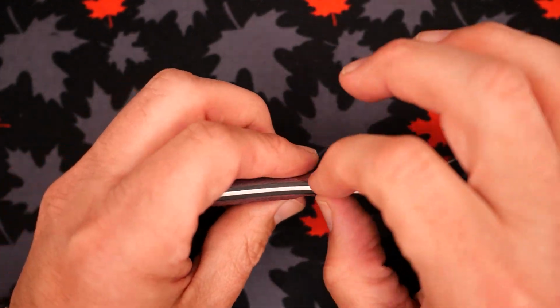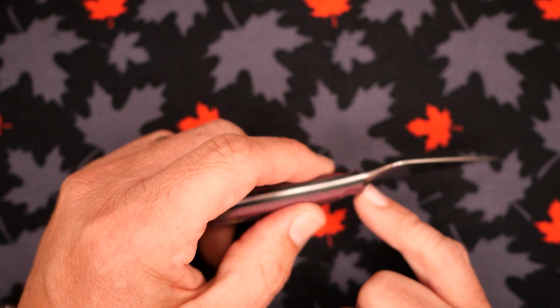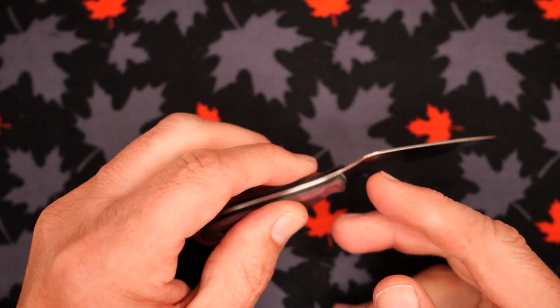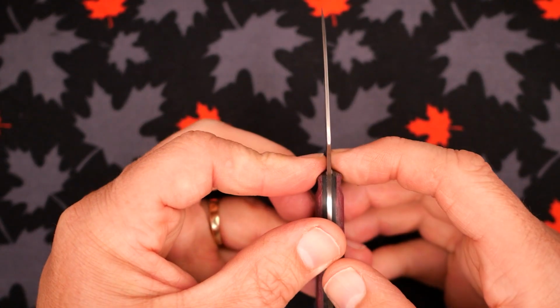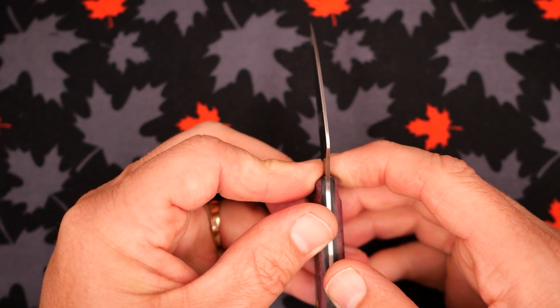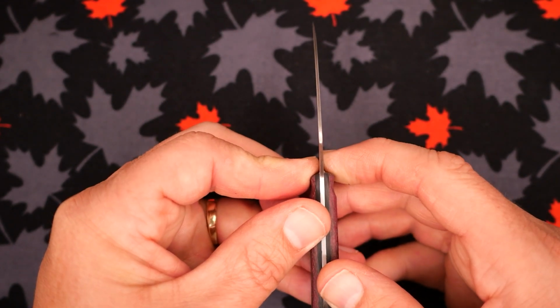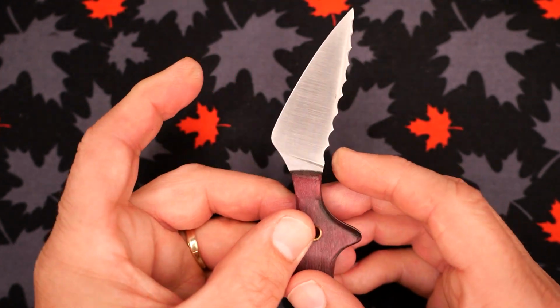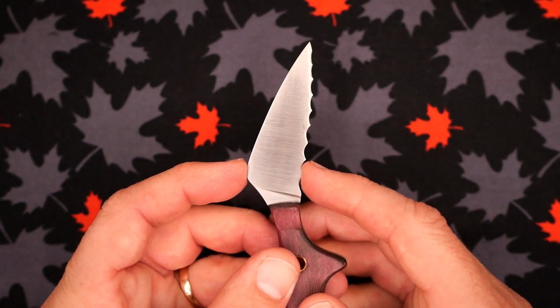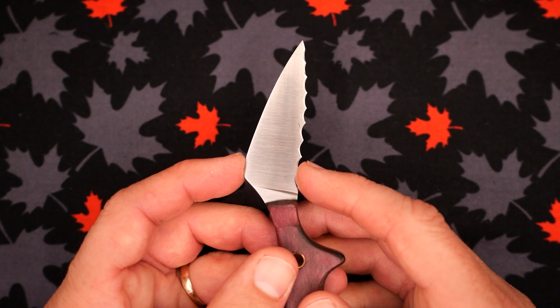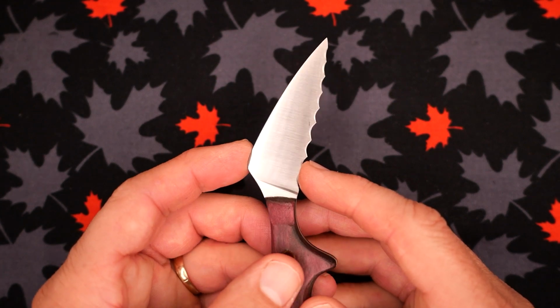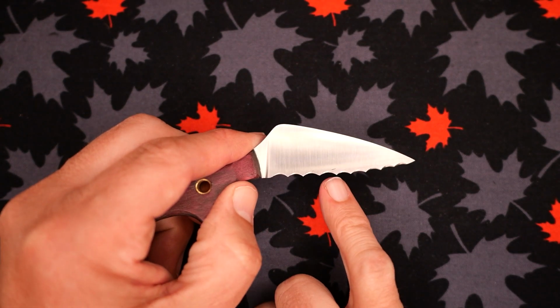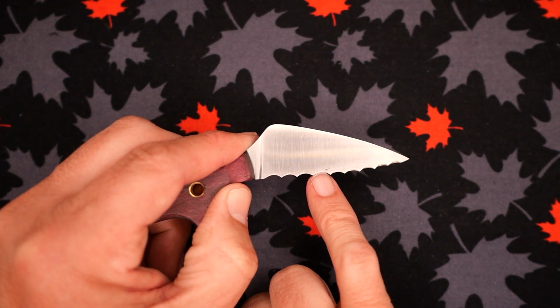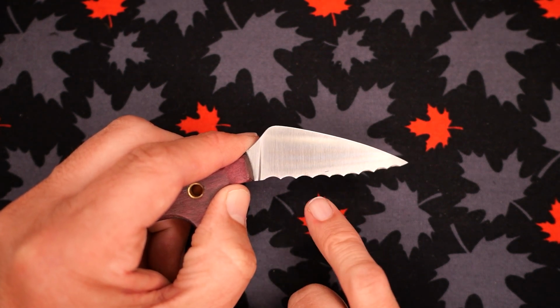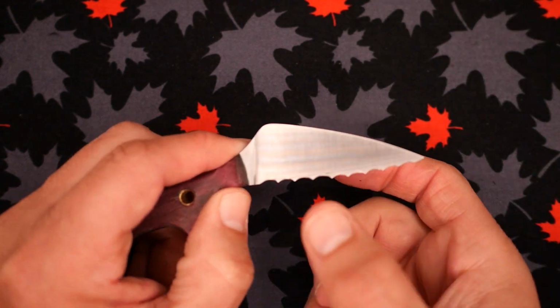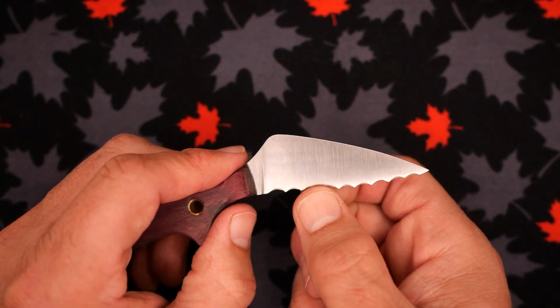The blade thickness, and right here you've got the nice ricasso there. You can measure it easily how thick it is. 1.47 millimeters, which is 58 thousandths of an inch. The blade depth, of course, it's widest right here. That's 22 millimeters, 0.86 of an inch. Thickness behind the grind, well, at the back of those serrated scallops, those serrations, that's where it's thickest, at the back of the edge. That's 0.28 millimeters, 11 thousandths.